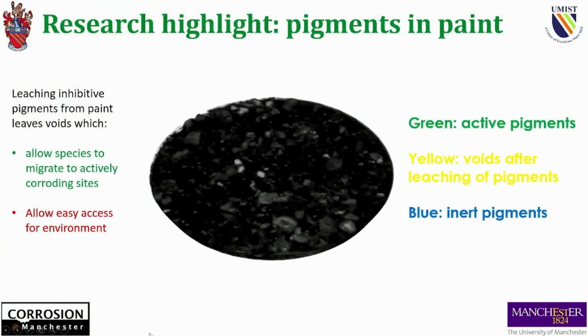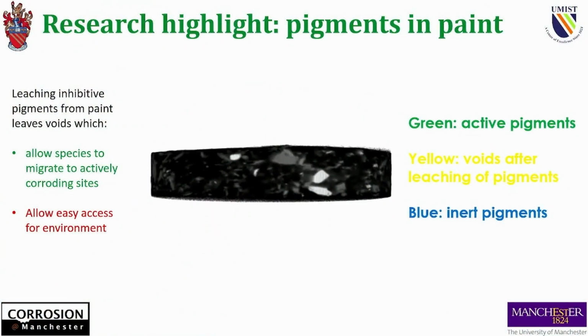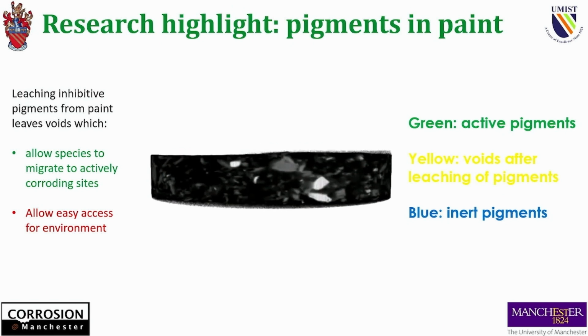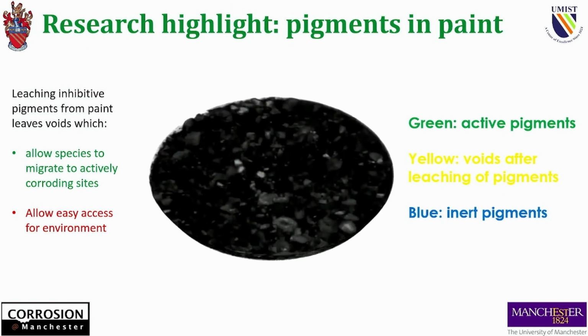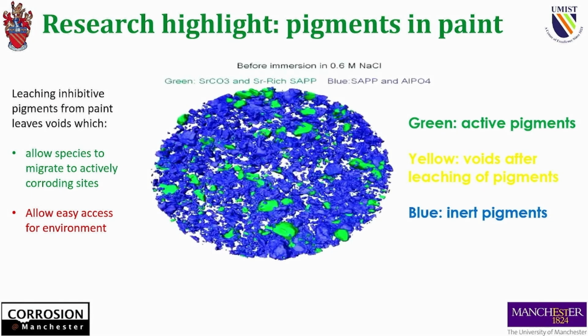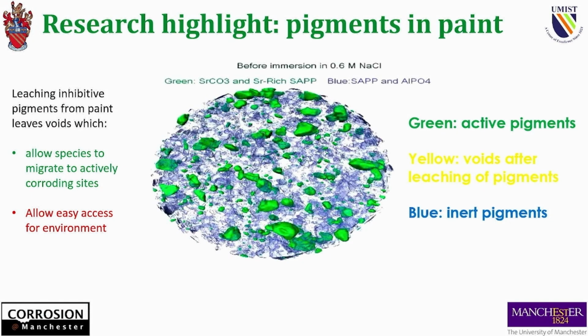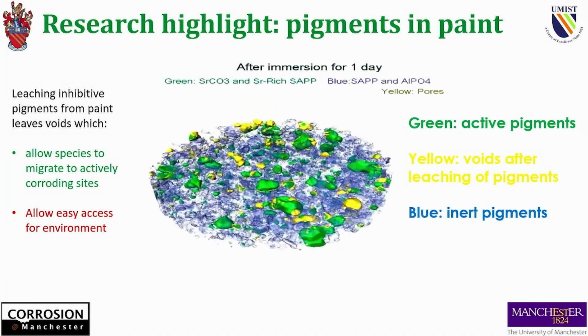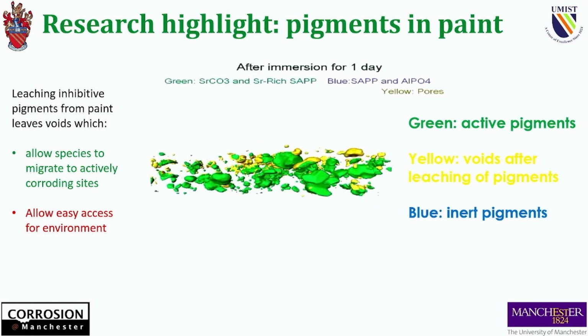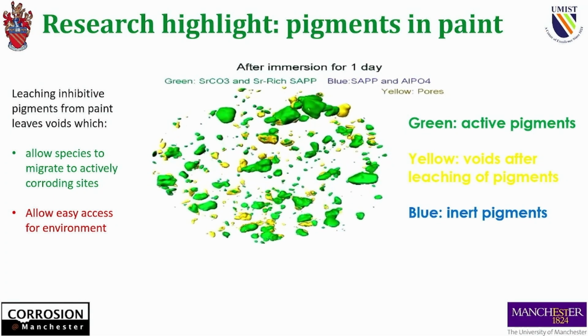This is a piece of wire painted at the end, a rod, and that's the X-ray density map. Because the density is dependent on the absorption, the density is dependent upon the atomic number. We can separate the components of the paint out. What's happening here is we're just segmenting the image on a grayscale to remove the things that we're not interested in. So after one day, just kind of stop it.